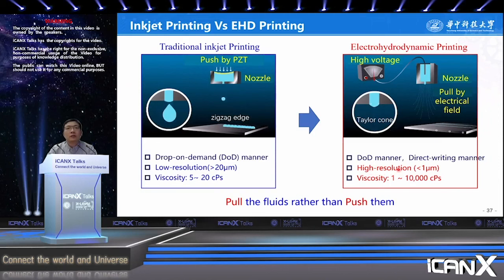However, for EHD printing, a high voltage electric field is applied between the nozzle and the substrate. The applied voltage can polarize the solution at the tip of the nozzle and pull the ink from the Taylor cone. EHD printing pulls the fluids out of the nozzle rather than pushing them. EHD printing deposits structures in a drop-on-demand manner, like traditional inkjet printing, or in a continuous manner. The resolution is smaller than 1 micrometer, about 2 orders higher than traditional inkjet printing. And the viscosity is from 1 to 10,000 cP, about 3 orders larger than that of traditional inkjet printing.